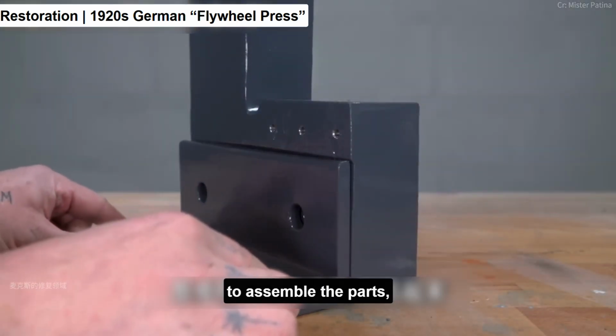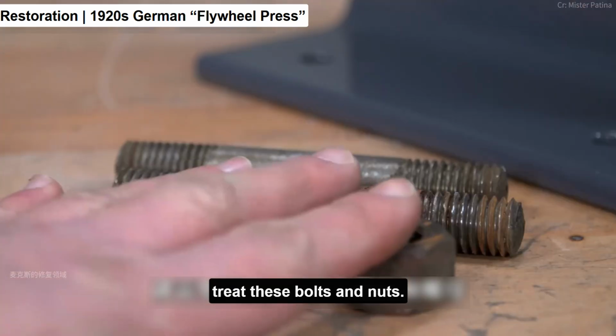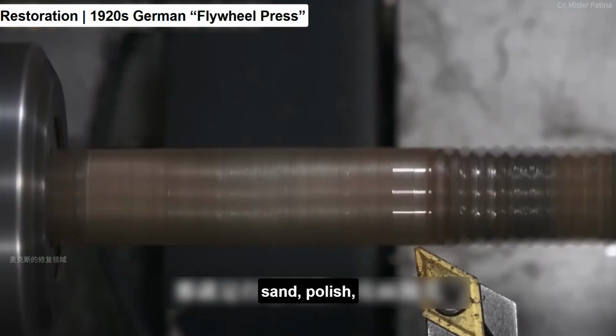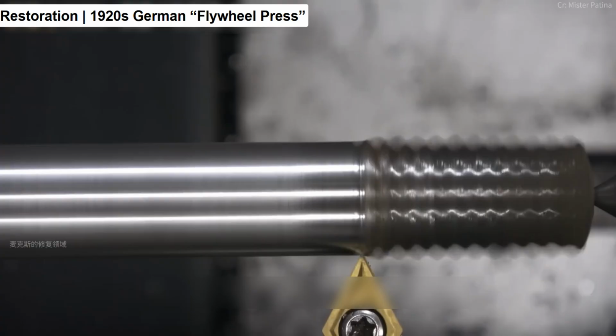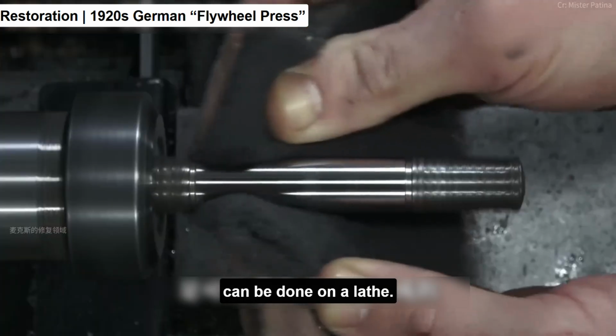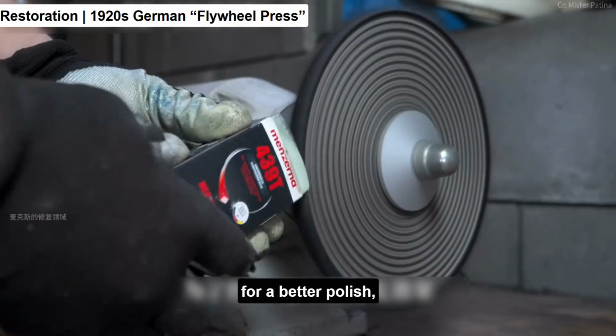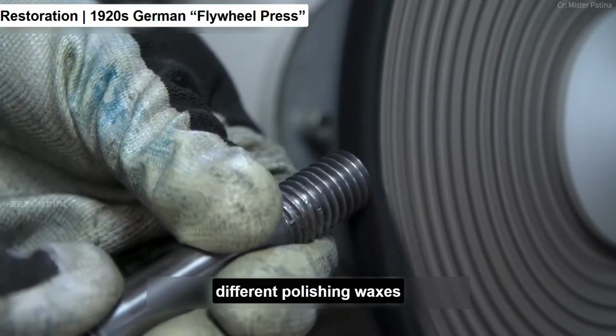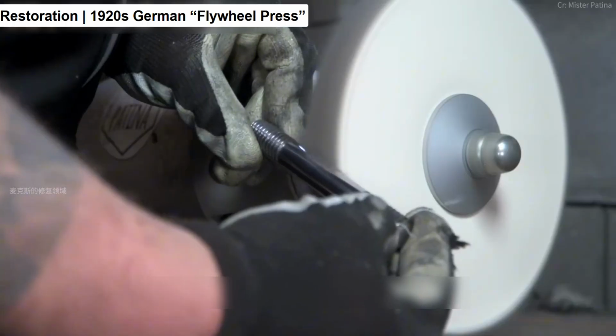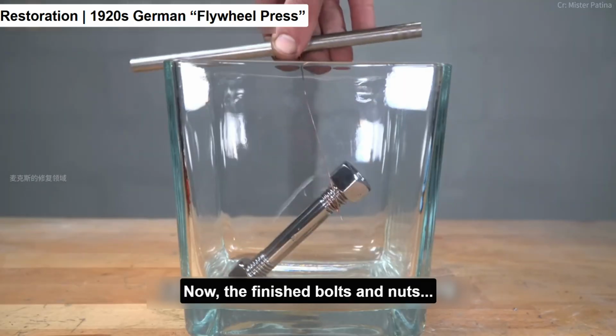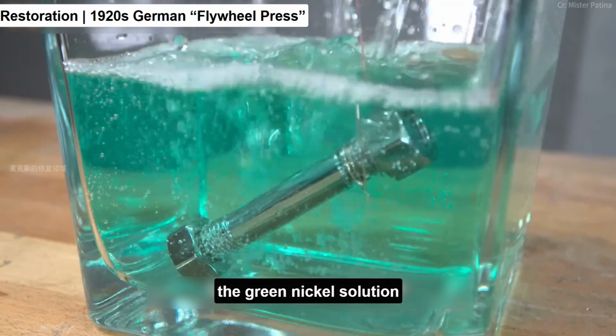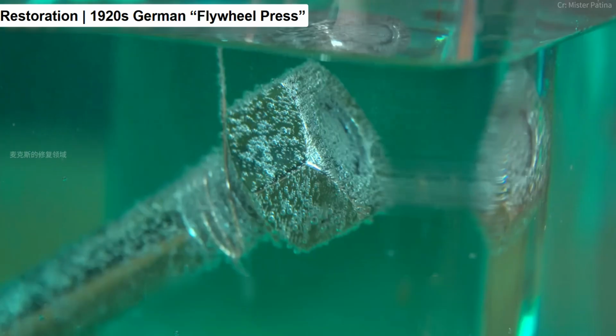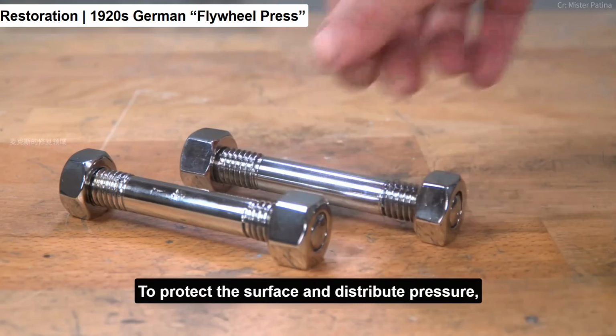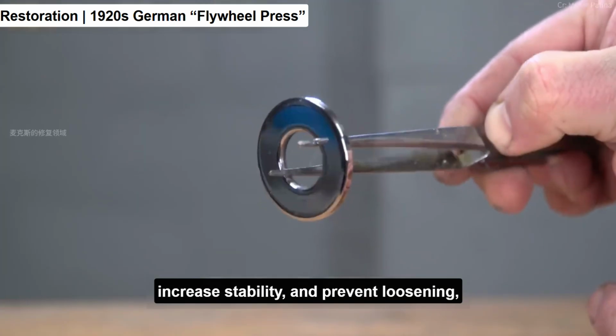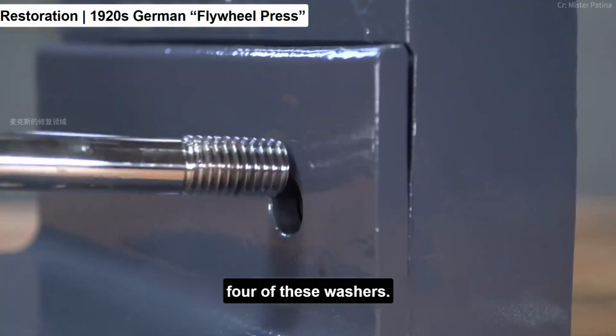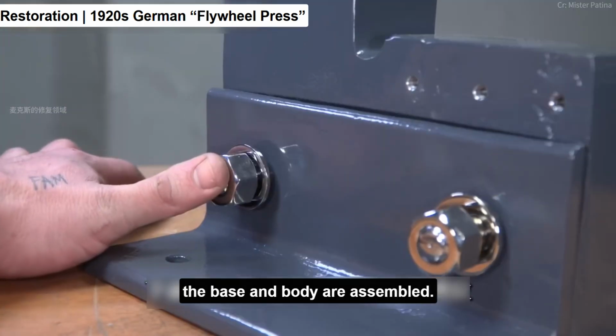After painting, to assemble the parts, treat these bolts and nuts. For these fasteners, we know the drill: sand, polish, and nickel plate. Due to their shape, the sanding step can be done on a lathe. For a better polish, he uses 3 different polishing waxes to finish the job. Now, the finished bolts and nuts are placed into the green nickel solution for the plating process. To protect the surface and distribute pressure, increase stability, and prevent loosening, Patina also made 4 of these washers. With the fasteners ready, the base and body are assembled.